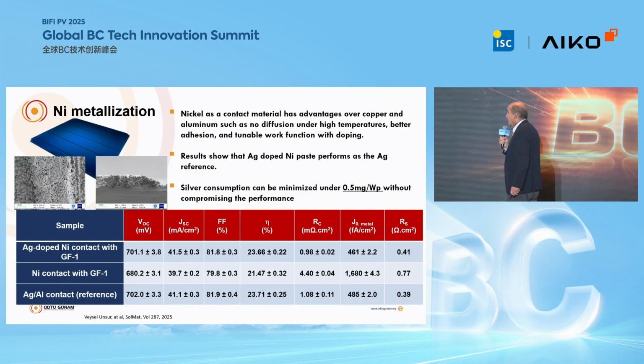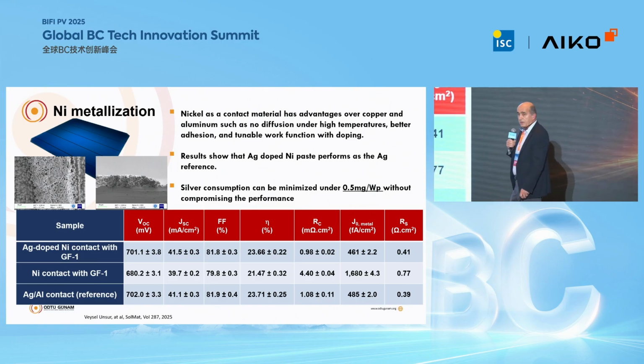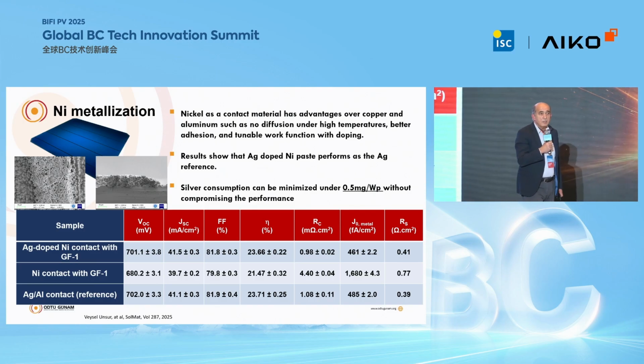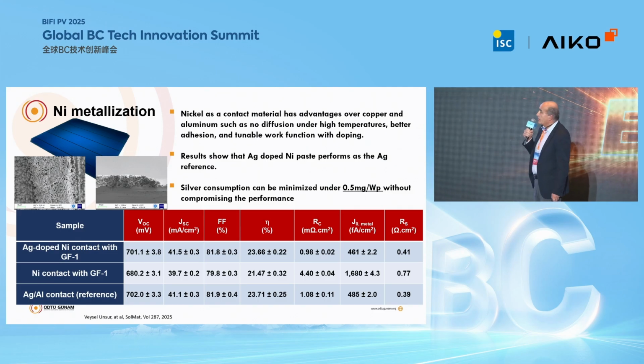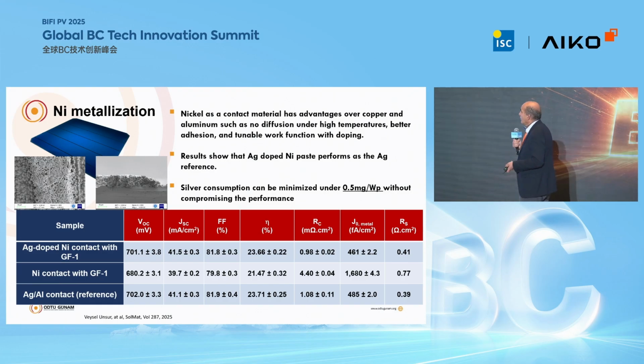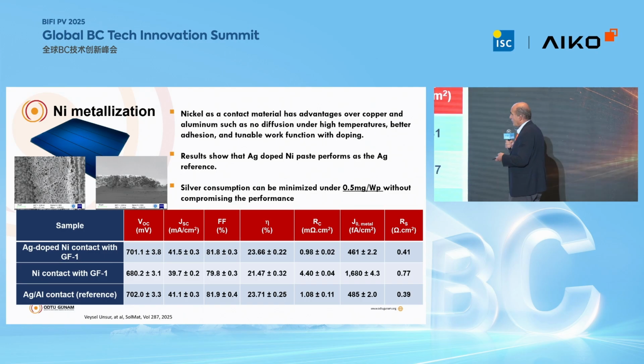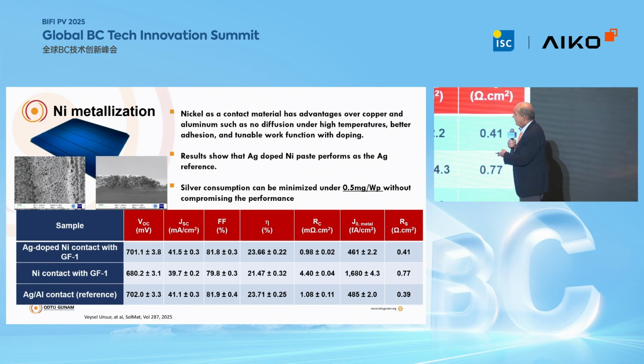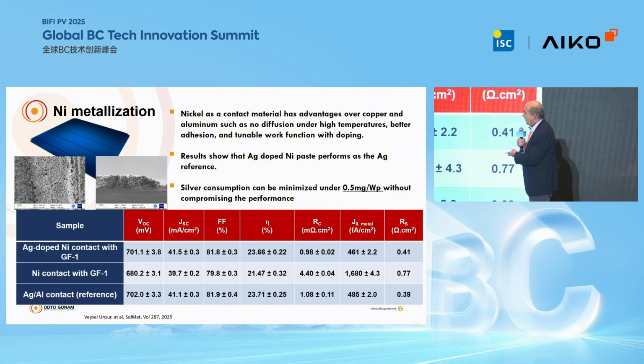So I just want to mention a few words about nickel metallization. Nickel is a good metal, actually. It has some advantages over copper and aluminum, diffusion is less at high temperatures, it has good adhesion, and the work function can be adjusted somehow. So in this work, which is published here, we have tried two cases. One is pure nickel metal, the other one is silver-doped nickel.